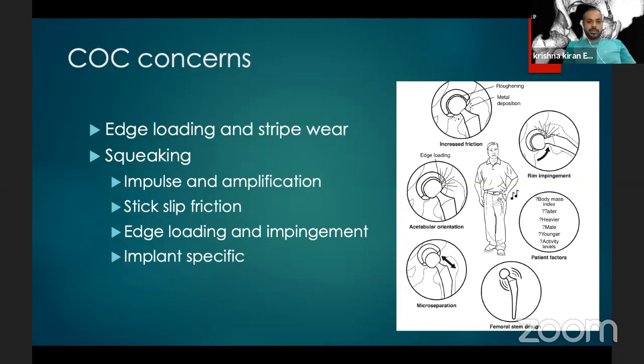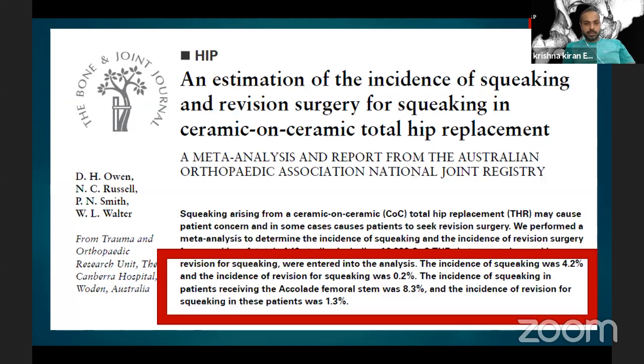Squeaking is another concern with ceramic on ceramic, and that's the noise. You can hear the noise. It generally indicates that there is some serious problem, in rare cases a fracture of the ceramic liner. When they analyzed the incidence of squeaking, it was 4.2%, and the incidence of revision for squeaking was 0.2%. So this must be explained to the patient if we are considering ceramic on ceramic. We must not use the Accolade femoral stem with ceramic, because the incidence of squeaking is almost twice as high, and the incidence of revision is about 6-fold higher compared to other stems.